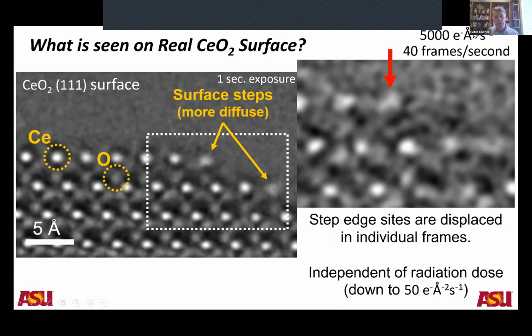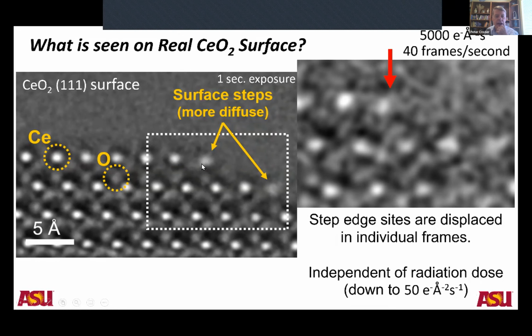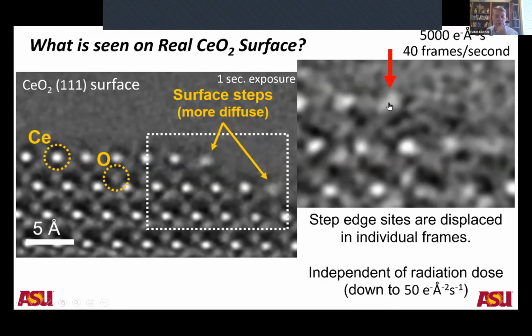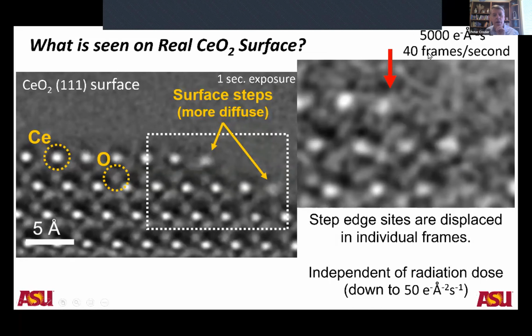This is 5,000 electrons per angstrom squared per second, which is below the critical dose that Bob Sinclair and his group determined for ceria at Stanford of about 7,000 or 8,000. And what you see is that even though the image is clearly noisy, these being individual frames, the fuzzy ceria atom column you see here is actually moving around, moving back and forward. When Chris was talking, I realized that if I show a molecular biologist 5,000 electrons per angstrom squared, they'll immediately claim this is all radiation damage. Ethan did check this. It makes no difference all the way down to 50 electrons per angstrom squared per second. So that instability is not primarily caused by the electron beam.